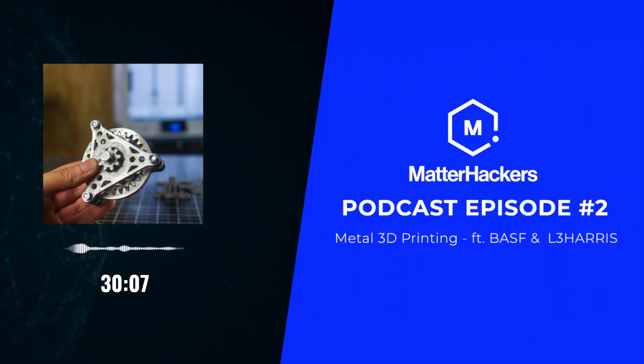Once we get that part that comes back, we enter the other two blocks to the right of that, where the adjusted scale value and the adjusted green part value, those automatically update what we really should have scaled the part to. And so we use this quite a bit. Once we hone it in, then we know what the scale values will be for thin parts, medium height parts, tall parts, because we're finding those values are slightly different as we get into this.